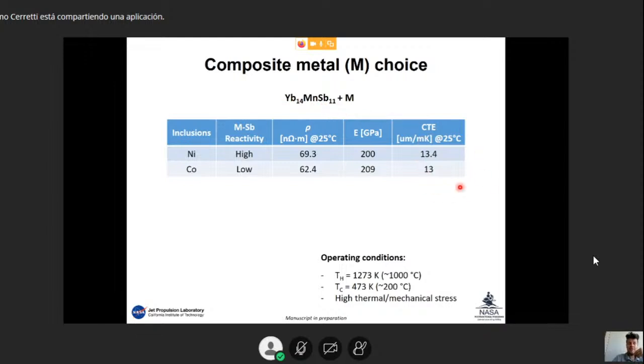The coefficient of thermal expansion is an important parameter when we make composites, because if the mismatch of CTE between the matrix and the inclusion material is high, that might generate internal cracks and lead to failure of the material. When the material is exposed to high temperatures, one material expands more, the other less, and where the temperature is lower, one material shrinks faster than the other, and this difference in expansion and contraction can generate cracks in the material.